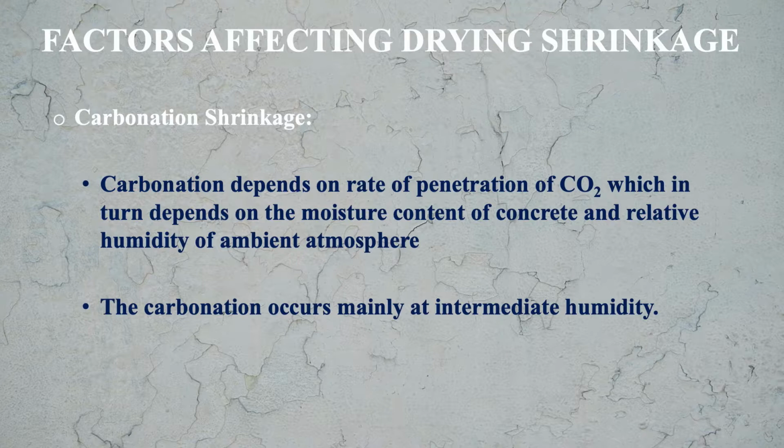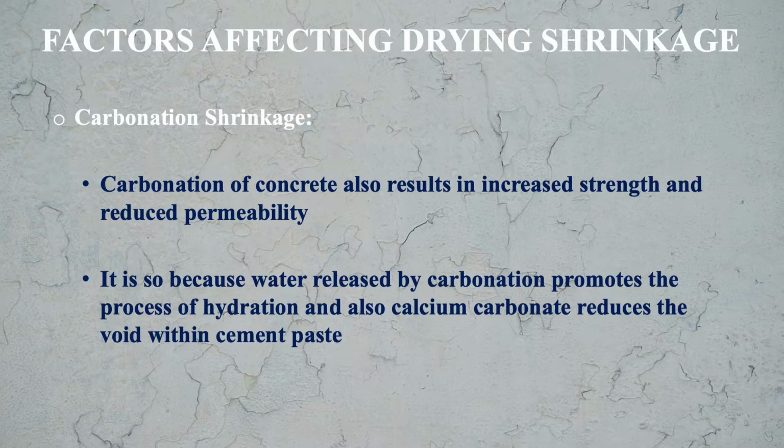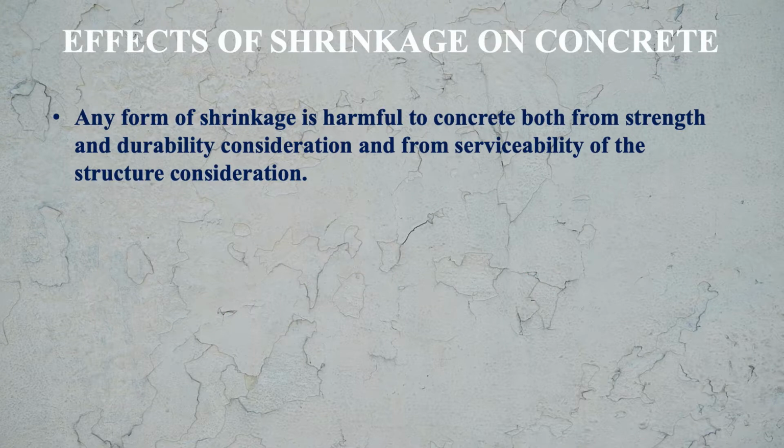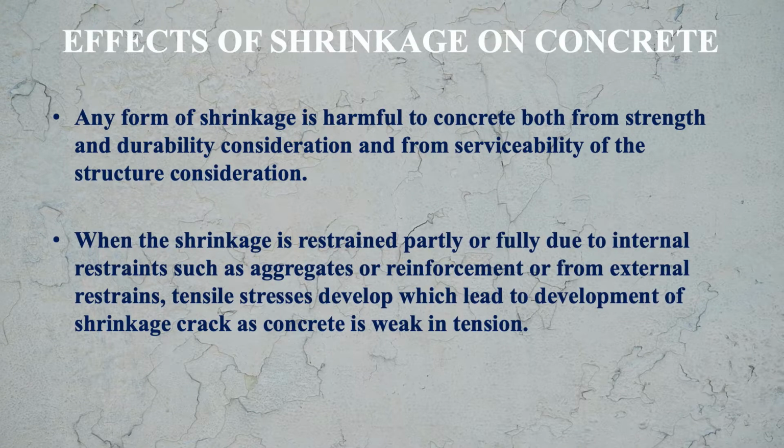Carbonation depends on rate of penetration of carbon dioxide, which in turn depends on the moisture content of concrete and relative humidity of the ambient atmosphere. The carbonation occurs mainly at intermediate humidities. Carbonation of concrete also results in increased strength and reduced permeability. It is so because water released by carbonation promotes the process of hydration, and also calcium carbonate reduces the voids within the cement paste.